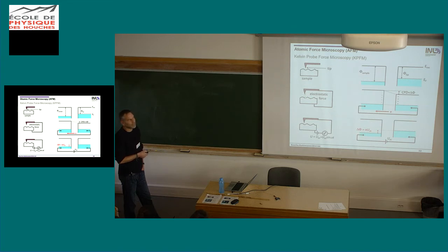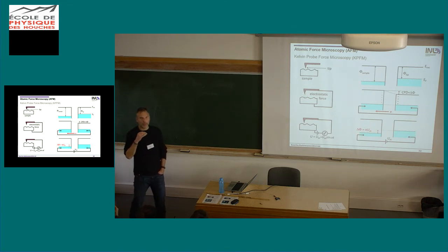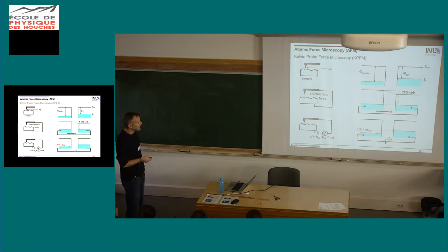And of course, this electrostatic force we can detect with our tip. It's a force sensor, right? So when we apply a DC bias that corresponds to the difference in work function, we can align the vacuum levels again, and we get this step here in the Fermi level. So this is the same, but this time it's connected electrically with a bias here. And in this case, again, we don't have any electrostatic force.